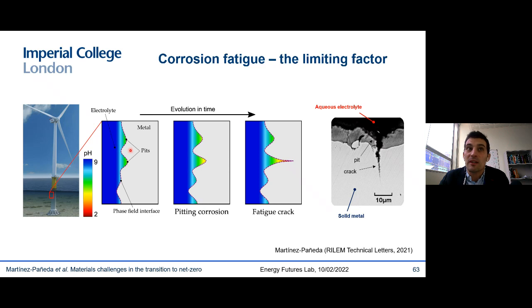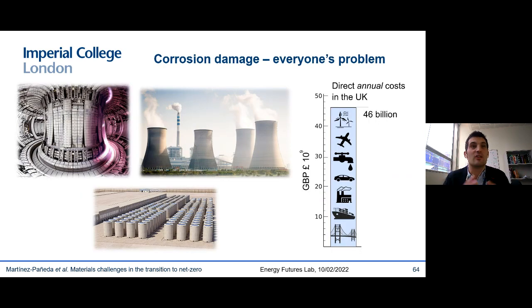So the shape of these pits depends on the local chemistry and mechanics. So they will grow faster if you have higher mechanical fields, or they will grow faster if they have a lower pH and so on. However, the local chemistry and mechanics are also affected by the shape of those pits. So this is a very strongly coupled problem, and you need to be able to resolve that interface evolution and all the physics and chemistry that comes with it. And this is, of course, in addition to the challenges that are inherent to both fatigue and corrosion, right?